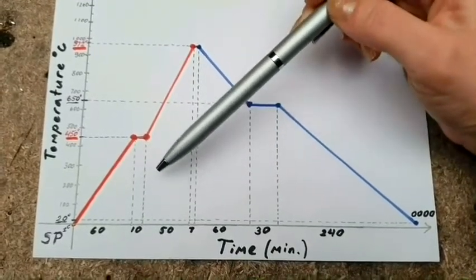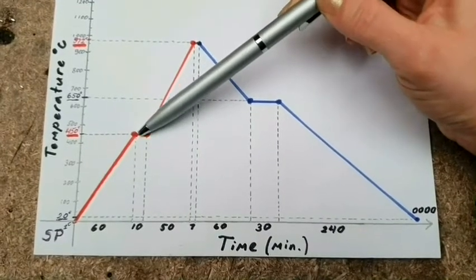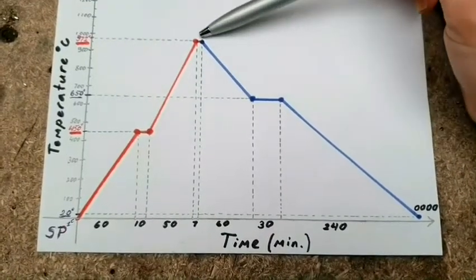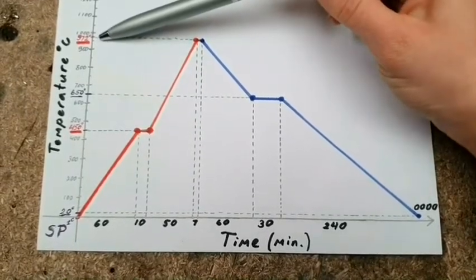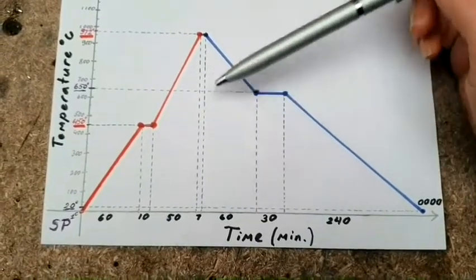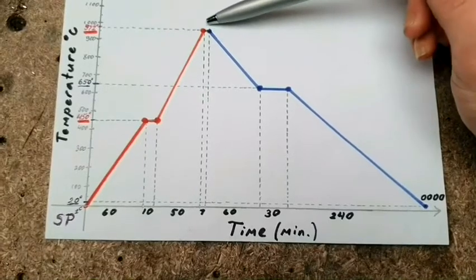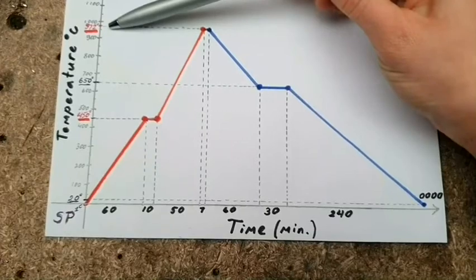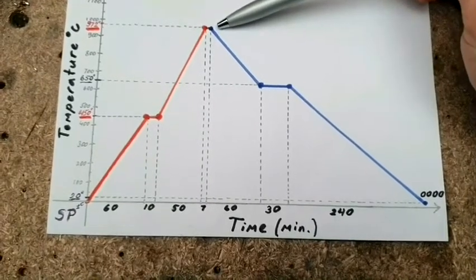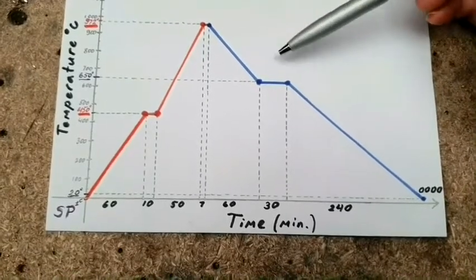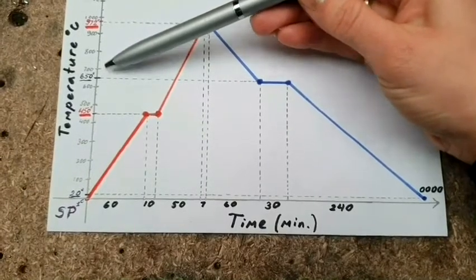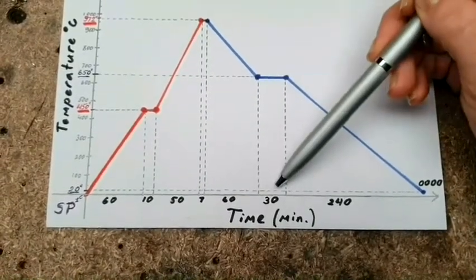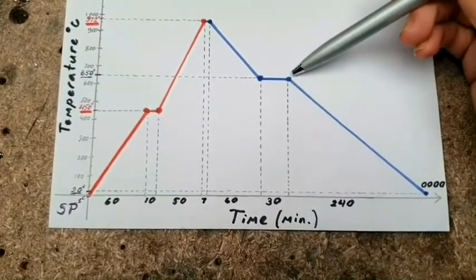So I put 450 degrees at the end of soaking time. The next one I entered 972 degrees then I enter 7 minutes which is my soaking time when I entered 972 degrees again to end of my soaking time. And the same I do to the last one. I entered 650 degrees then 30 minutes and then 650 degrees to end of my soaking time.